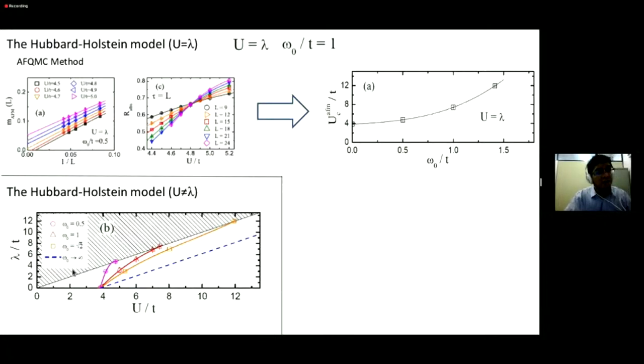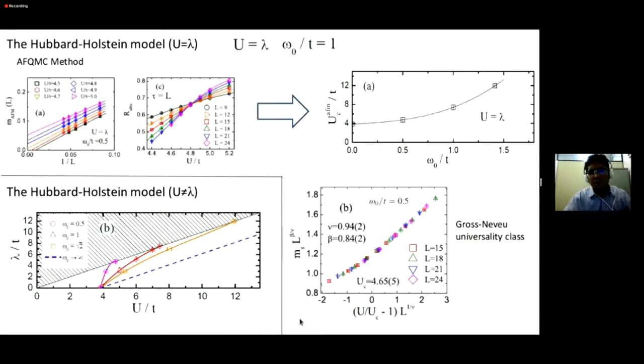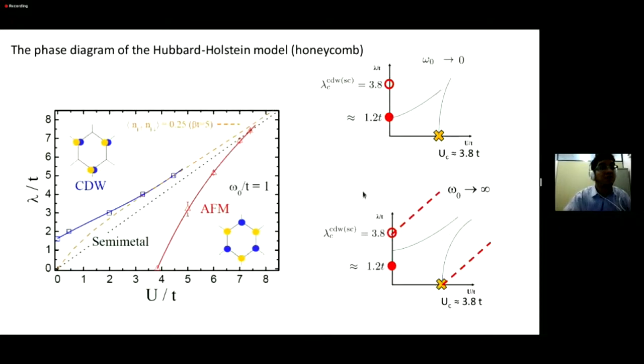So what we saw here was basically that the critical points for the honeycomb lattice are strongly dependent on the phonon frequencies, as we presented here. We also analyzed, but here we are not going to discuss this point, the universality class of this transition, but it is the regular one, the Gross-Neveu universality class. And similar to the square lattice, we also present one phase diagram for this case.